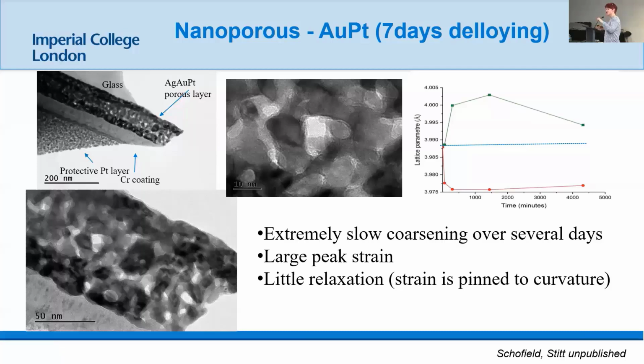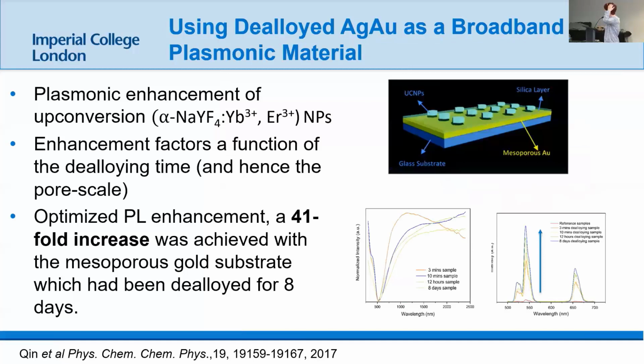And so functionally, you are also changing lots of really useful properties about these materials by controlling the pore size, because that controls the strain, right? And these things are all connected, all right? So often when people talk about nanoporous materials, they only think about surface area or the size that you could use for a filter. But actually, you're changing a lot more fundamental stuff when you do that. And so there's a couple of examples where we've used this as a useful entity.